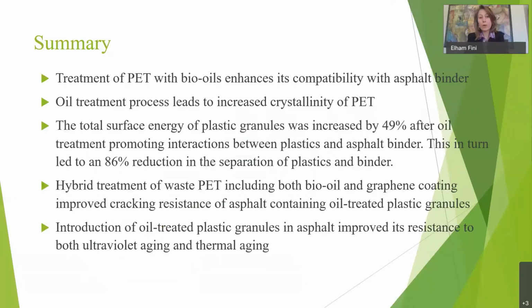But overall, we found that including the PET or end-of-life plastics in asphalt roads helps, provided that it is compatible. I want to make sure this qualifier is there, because you cannot just grind and dump plastic into the construction material because they're not compatible. And they're going to separate, segregate, and it will be a disaster. So I would make sure if we are using end-of-life plastics, that it's compatible. And that's what I put in the first bullet here. We show that oil treatment improves the crystallinity of PET, so you actually get better granules than the non-treated one, which then gives you better stiffness and better properties in your composite.